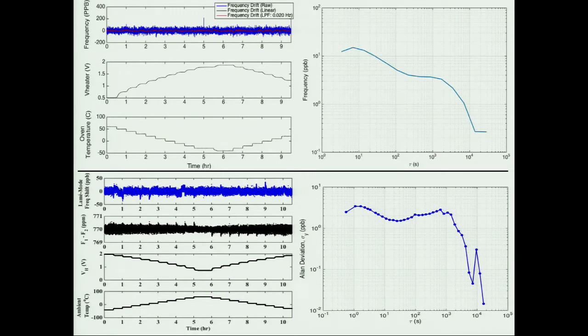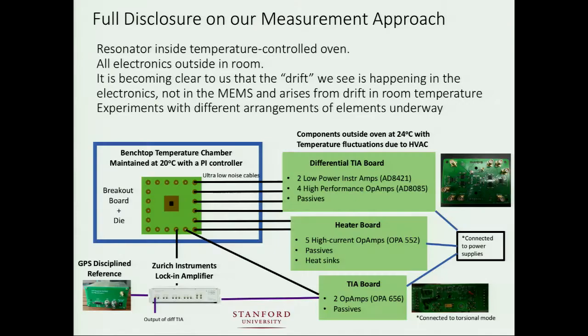So a little bit of full disclosure, we've done this a bunch of times. We got a bunch of data. It's generally pretty consistent, but we have some issues with the performance of our feedback controller. Things happen in the lab on an average day. Someone slams the door, someone pulls a plug. You know, it's a lab environment in an academic world, so there's glitches, and the glitches dominate what we see. But over and over again, over time periods of many hours, we're seeing Allan deviations just keep going down the longer we look. There's no inherent drift, and we're able to fix most of the temperature coefficient of all this. We're looking at stabilities that are around 1 part per billion over a pretty wide range of time scales, which get better as you go further out.